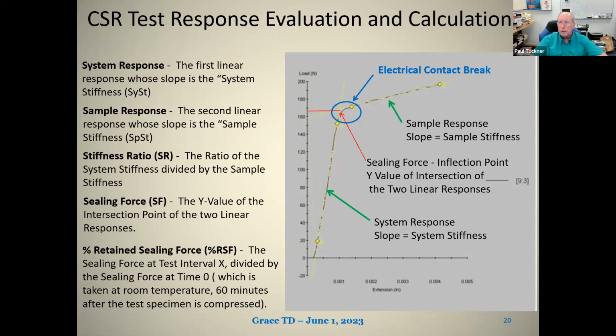One of the things this allows is that if you're doing sample stiffness, you can note that over the test period the sample stiffness may change. Some materials that age by diffusion limited oxidation will have an increase in sample stiffness over the testing period. Let's say if you're doing nitrile testing aged in air, you'll see that sample stiffness increase. At some point during the testing, you may find that your stiffness ratio gets too low that you can't see an inflection point, and that can happen in certain cases. So having a good load deflection curve response and knowing what that means is really important in getting good CSR results.